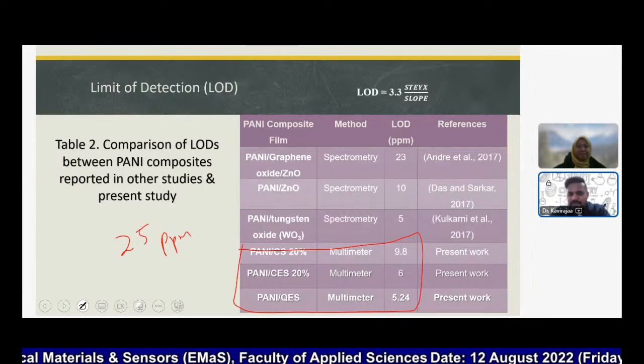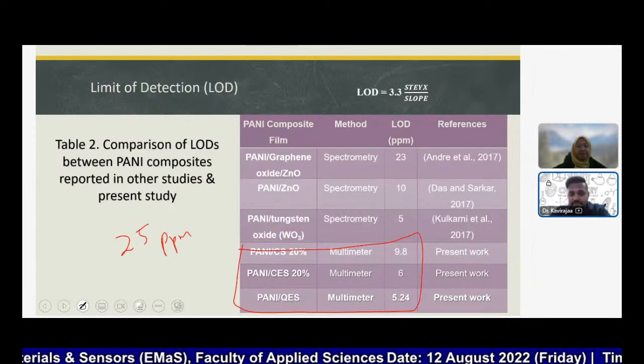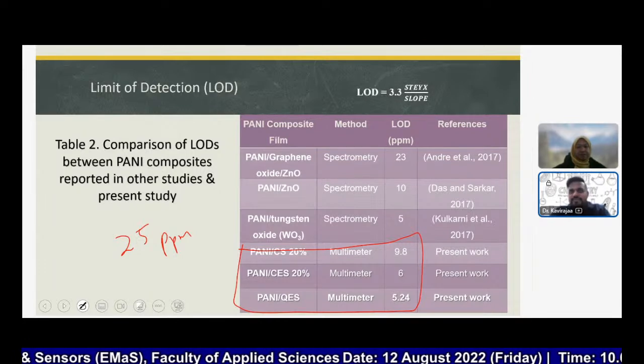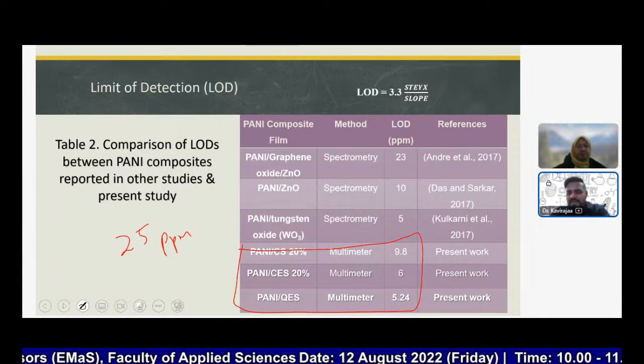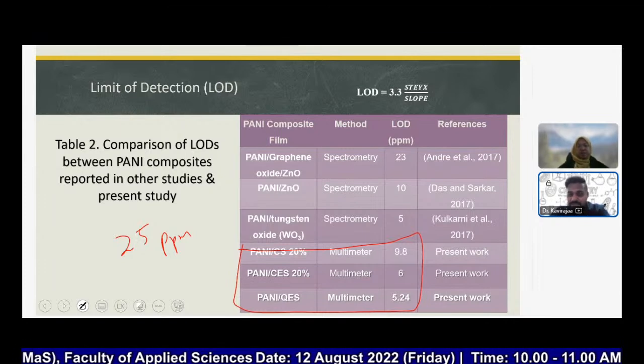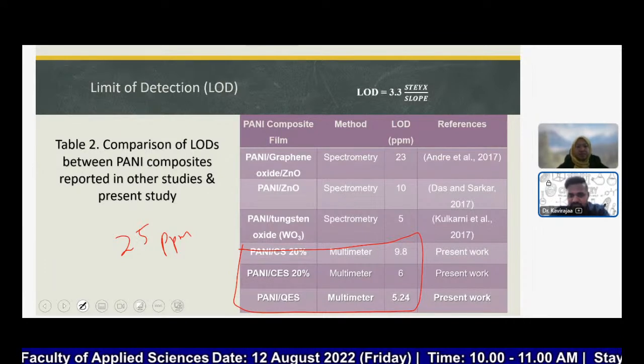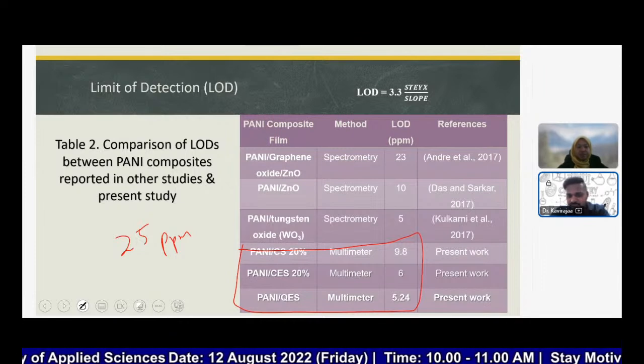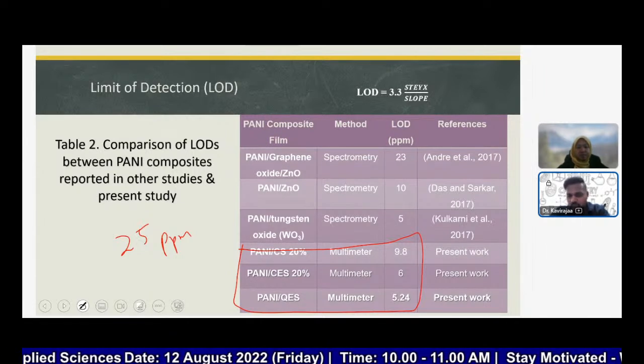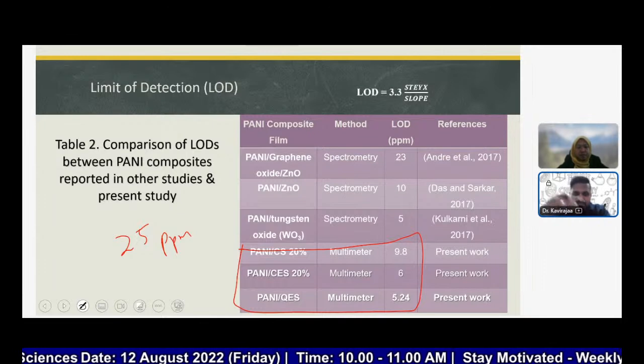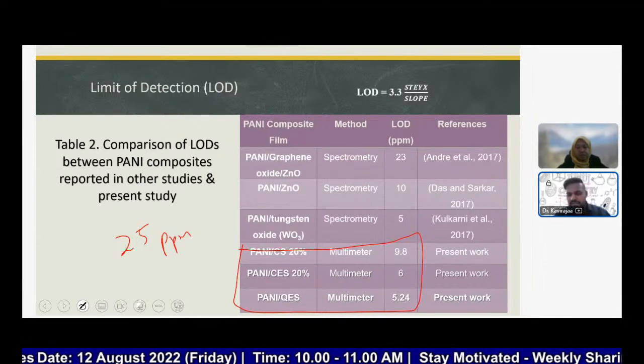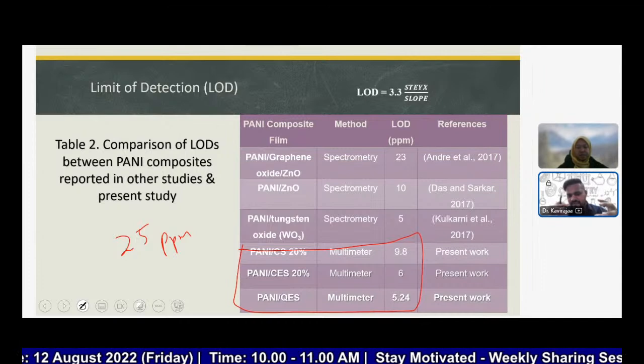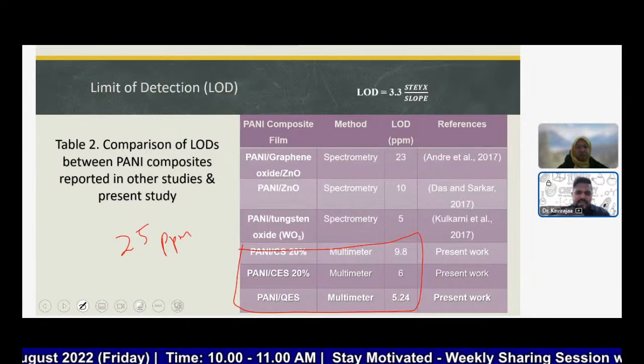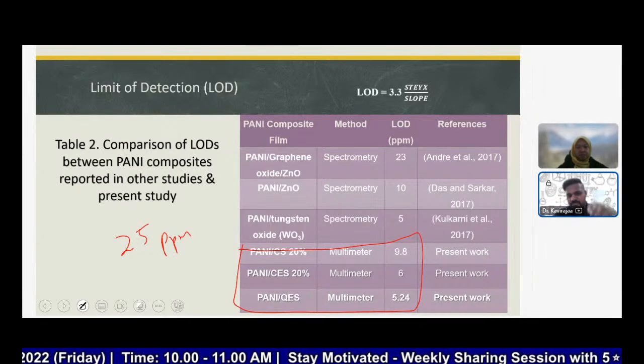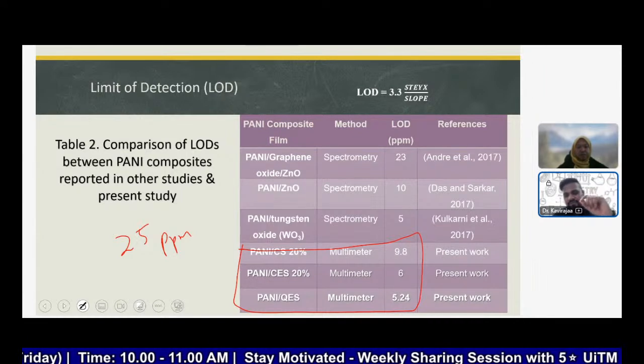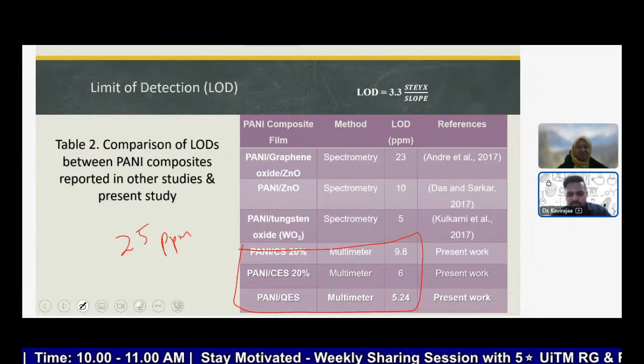It's showing some response after we have added, because pristine PANI, it fluctuates. Every time we synthesize, sometimes we get like 50 ppm, sometimes we get 70 ppm, the limit of detection for the pristine PANI. But after we have added the shells, it improved. Why? Probably because these shells went in between the tangled polyaniline chain, and then it maybe made it kind of expanded. So it maybe made the electrons move much easier, so that the polarons, because the polarons are the ones which will react with the ammonia.